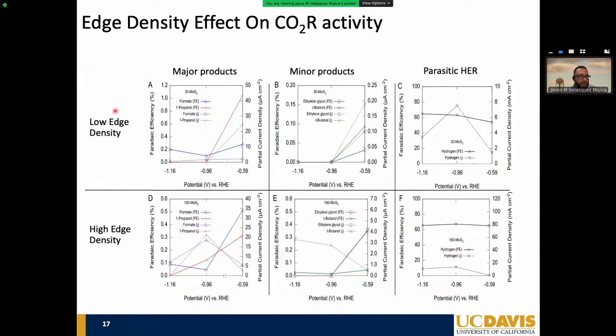And when I label low edge density, that is the top-down SEM image that you'll see in the next slide, that has little to no edge sites, little to no under-coordinated molybdenum sites, versus something that has just a high number of edges. And the interesting result here is indeed, we're seeing propanol in the liquid phase, and actually even for the low edge density, so with little to no edges, the Faradaic efficiency towards producing propanol from CO2 is close to 1%. The majority of the partial current is being utilized to produce hydrogen evolution.